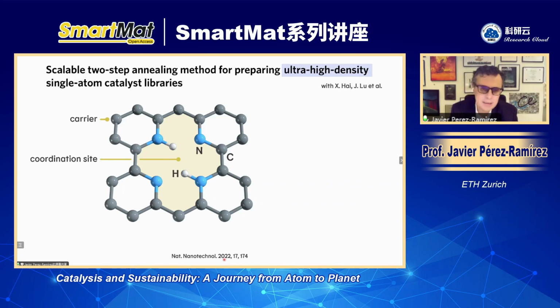You have here a carrier. This is a nitrogen doped carbon. And you see here the hydrogen functionalities connected to the nitrogen. And this is actually the place where you could stabilize the single atom by creating a bond between the metal atom and the nitrogen, basically replacing hydrogen by your metal. And that's what we call the coordination site. This is the place where you can anchor the metal.